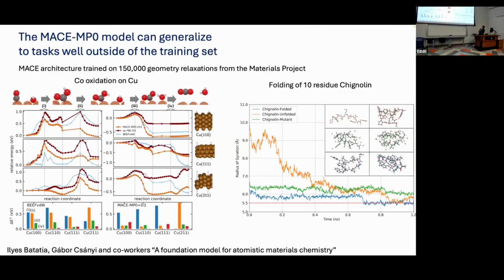What's also surprising to me is that it can actually be applied to organic molecules, or was applied in this case to organic molecules. Here, this is chignolin, which is just a 10 residue fictitious protein, and it's being used to map the folding of the protein. This is the radius of gyration, and this is the unfolded protein that eventually, over some given time, folds. You can see that by this plot. So even though there are some carbons and hydrogens in the Materials Project because they're in some solid state systems, there are no proteins in the Materials Project, and yet it is able to be applied to that and successfully model this folding. So this is a quite interesting result: once the model has been trained to a very large system, it can start to generalize rules it's learned even to cases it hasn't been explicitly exposed to.